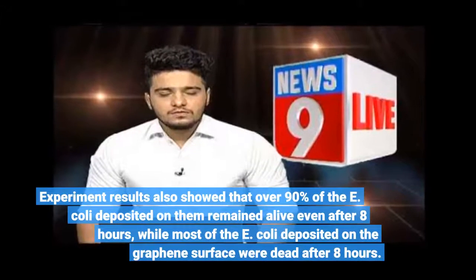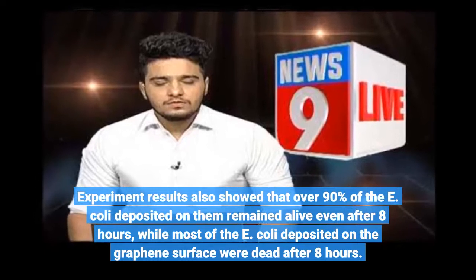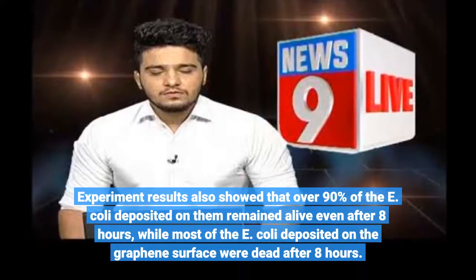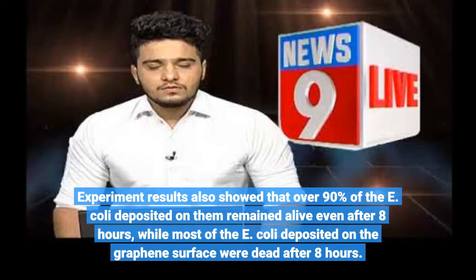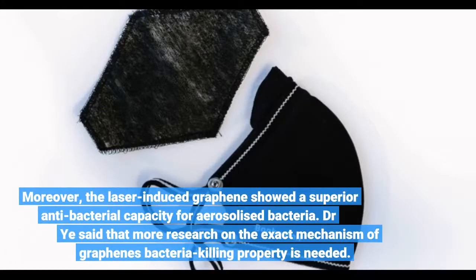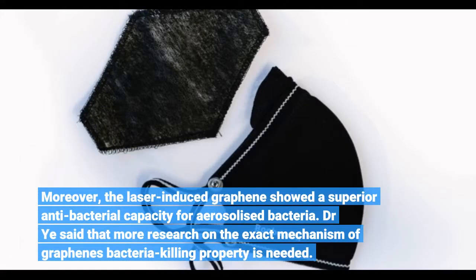Experiment results also showed that over 90% of the E. coli deposited on them remained alive even after 8 hours, while most of the E. coli deposited on the graphene surface were dead after 8 hours. Moreover, the laser-induced graphene showed a superior antibacterial capacity for aerosolized bacteria.